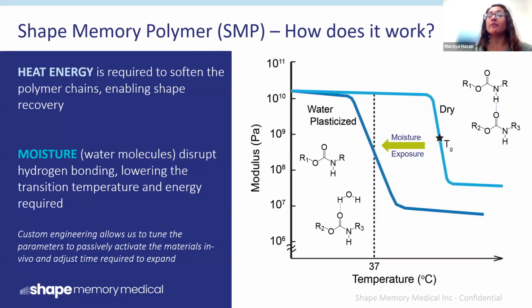The way the shape memory polymer specifically for us works is we're not just depending on the energy input or the heat input to cause shape change to occur. So typically with shape memory polymers, there's some kind of stimulus that causes the material to go from shape A to shape B. Our materials are thermally actuated, but we're also using to our advantage moisture plasticization. So what happens is once these devices are deployed in the body, you have elevated body temperature, but the dry Tg of this foam is around 54 degrees Celsius. So it's still way too high above the body temperature for any kind of shape change to occur.